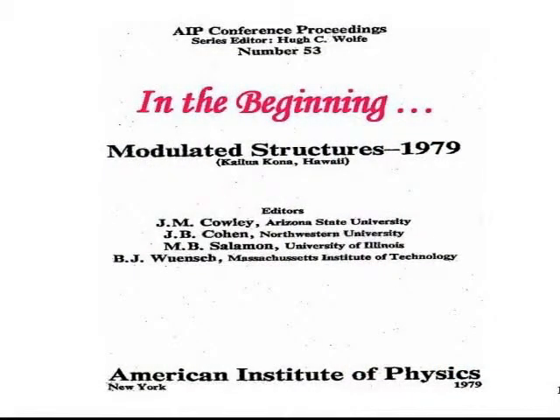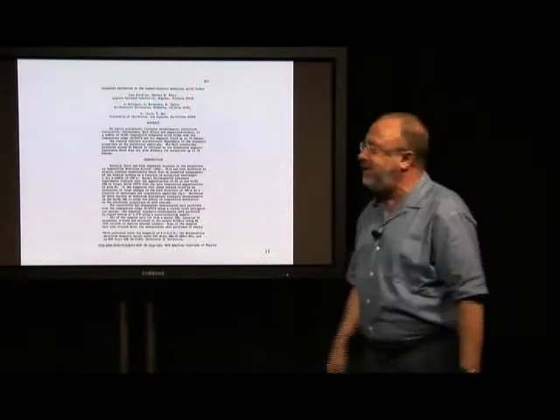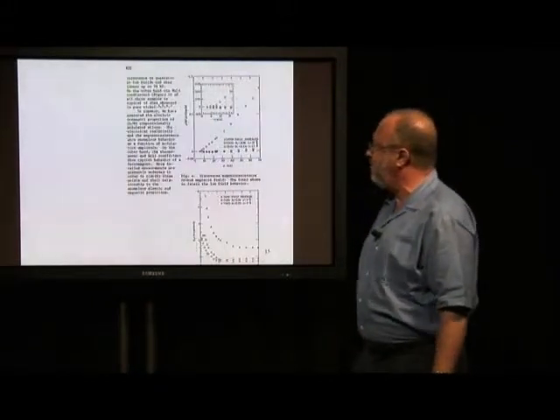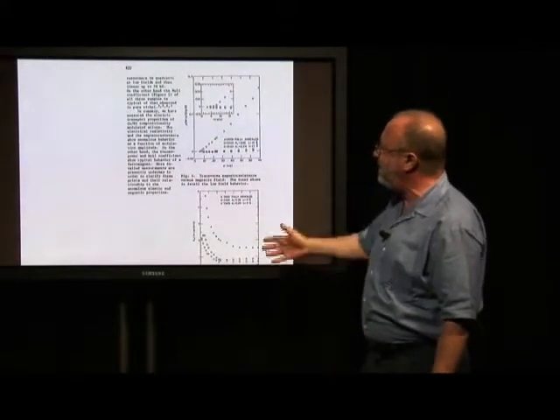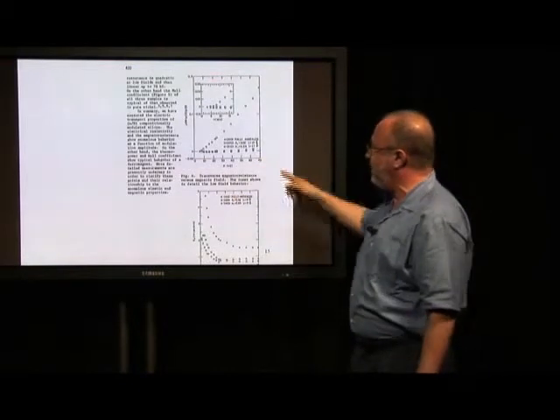Unfortunately, it was not a very widely read conference proceedings, but in that proceeding, I published this paper. I will not tell you the details of that paper, but it was on transport properties of the compositionally modulated alloy copper and nickel. It turns out that this paper did not get very much attention from people, but we published this paper in which we measured the magnetoresistance as a function of magnetic field